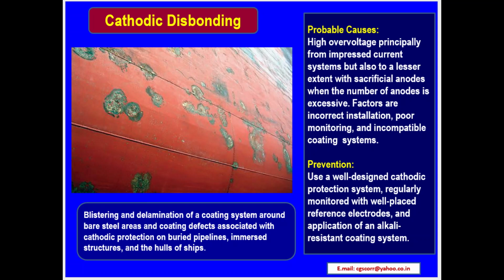Probable causes: high over voltage, principally from impressed current systems, but also to a lesser extent with sacrificial anodes when the number of anodes is excessive. Factors are incorrect installation, poor monitoring and incompatible coating systems. Prevention: use a well-designed cathodic protection system, regularly monitored with well-placed reference electrodes, and application of an alkali-resistant coating system.